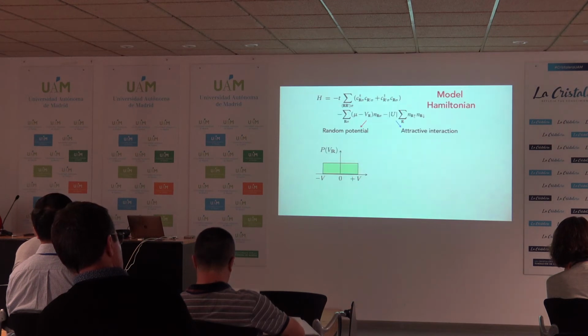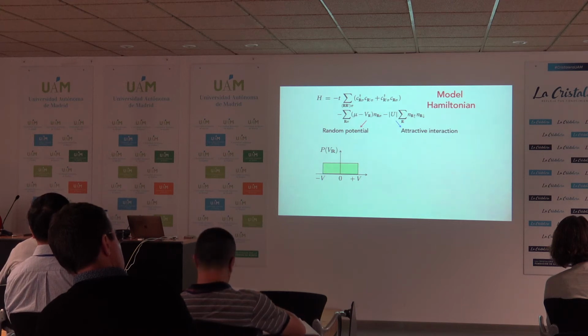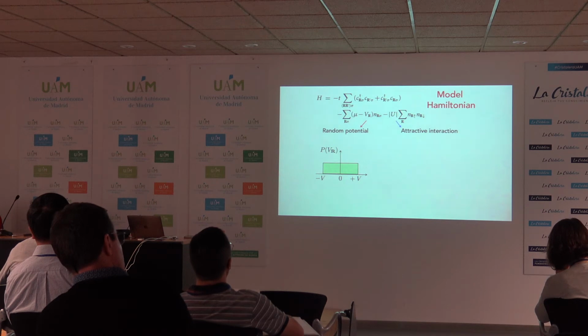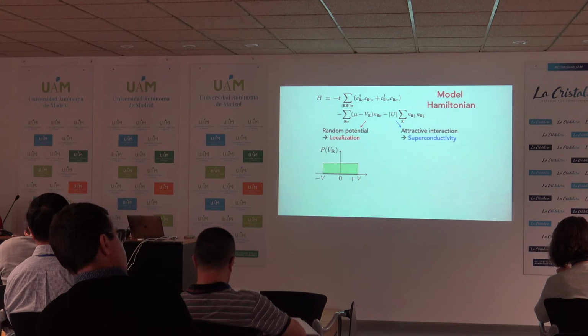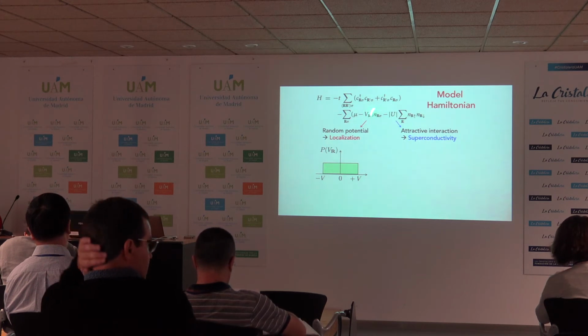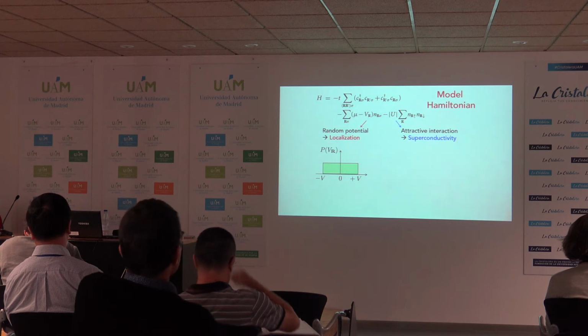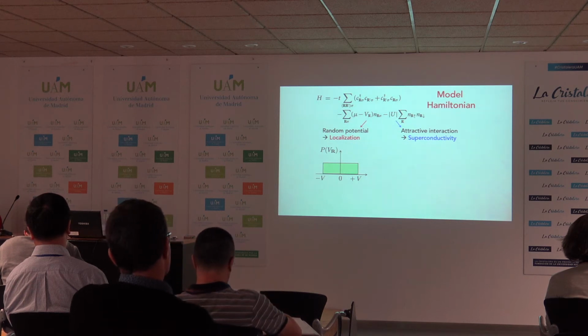Okay, now how do these things come out? This is the theory behind it. Here is the model now. It's an attractive Hubbard model. Now we revert back to a square lattice because we don't have competing orders when I have random potentials. The randomness is put in the chemical potential. And what is nice about this model is you can turn off the attraction and just study the localization physics, or you can turn off the random potential and then you have superconductivity, and all the BCS-BEC crossover is contained in the strength of U over t. So it's a really very nice model.